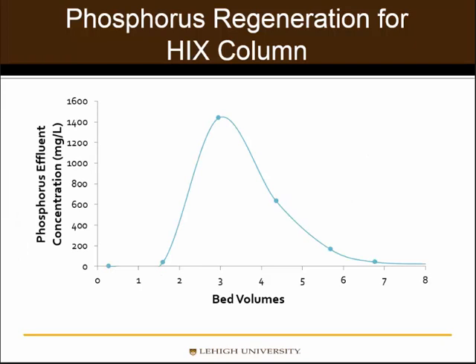So here's an elution curve that shows what we can do regardless of the source water, whether you're at 6 ppm, 40 ppm, 0.1 ppm out of a pristine lake that's been impaired with algae. You'll always end up with this curve if you've got a fully saturated media, where the peak point is about, well, I'll call it 1500 as PO4 orthophosphate. So that's equivalent to about a 0.1% P2O5 fertilizer solution.